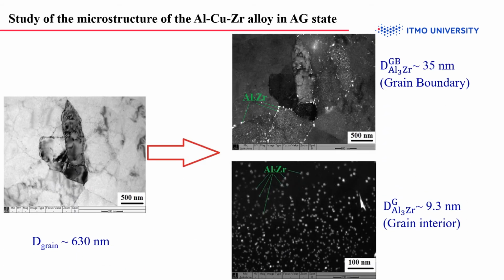The transmission electron microscopy analysis of the microstructure of the alloy in the AG state showed that the average grain size is 630 nanometers. The presence of a significant number of precipitates of the aluminum-zirconium phase, located both along the grain boundaries with average size 35 nanometers and in the grain interior with average size 9.3 nanometers, was revealed.